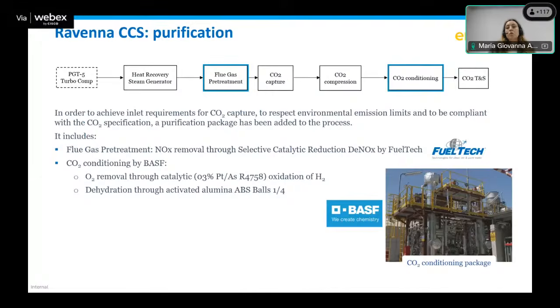However, there was also a need to implement another step for CO2 purification and conditioning, placed after CO2 compression. This includes the removal of oxygen. In this case, we implemented a package provided by BASF, including catalytic oxidation of hydrogen for the oxygen removal, followed by dehydration through solid adsorption on activated alumina. After the CO2 conditioning, the CO2 is sent to CO2 transport and storage operations.